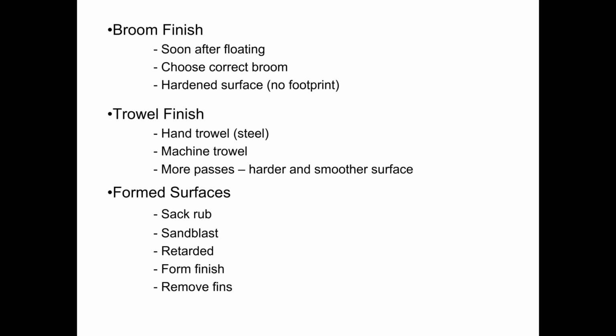So if you use a trowel when the concrete is still fresh, then you may be trapping moisture under that surface, increasing the water cement ratio of that surface, which leads to a weak surface that over time is going to peel and flake away. So we do not want to use trowels when a float should be used. So just keep that in mind.